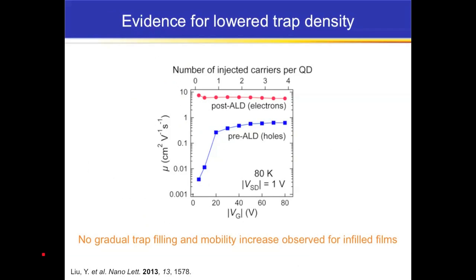We can get another indication that this is happening by plotting the mobility versus the applied gate field. For most disordered semiconductors, what you see is when you change the gate field, you're basically altering the Fermi level within the material. And you can drive the Fermi level close to one of the band edges, and you're going to fill traps when you do that. And so if you look at organic PV or organic field effect transistors, you'll see a curve that looks like this. This here is trap filling phenomena, and then finally you get to kind of a trap-filled mobility. And this is what our films look like before we do ALD. After we do ALD, we don't see any dependence of the mobility on the gate field. And this indicates to us that we have a fairly low trap density in these materials, very easily filled by just a small applied gate field at best.